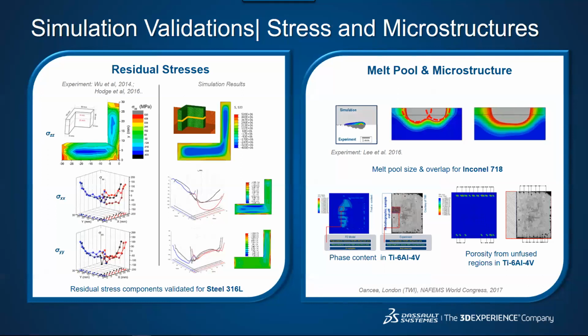And then we've also shown that we can look at microstructure predictions. For melt pool evolution predictions, we've been able to look at melt pool size and overlap due to interaction between laser beam and unfused powder. And again, we compared that with experimental results in literature.